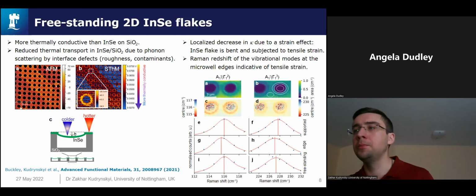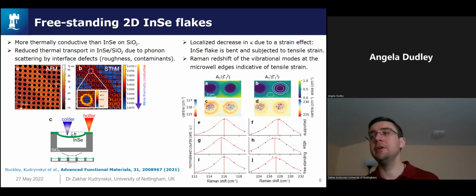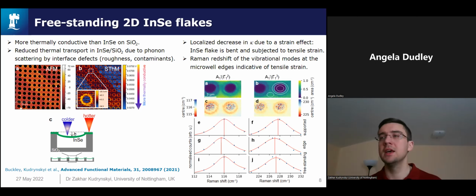There is also another important effect here occurring at the edges of the microwells. As we look carefully at the thermal images, the edges appear as bright yellow rings, indicating a lower thermal conductance compared to the substrate-supported and freestanding regions of indium selenide. While this could be a topographical artifact due to decreased contact area between a tip and the surface, it can also arise from the localized decrease of conductance due to a strain effect. At the edges of the microwells, the flake is bent and thus subjected to tensile strain.